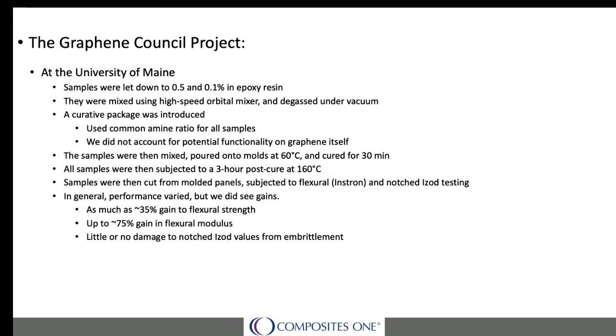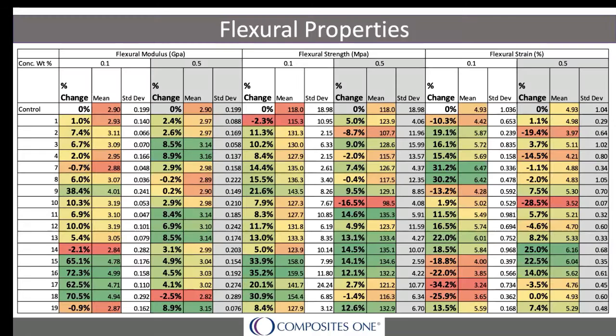In some of the samples, we saw great improvements in both flexural modulus and strength. Typically, when you improve the modulus of resins, you have a negative impact on toughness of the system due to embrittlement. And this was true for some of the samples. However, there were some that showed negligible impact to the toughness of the resin while providing excellent flexural modulus and strength improvements. So let's go ahead and dive into the details of the results.